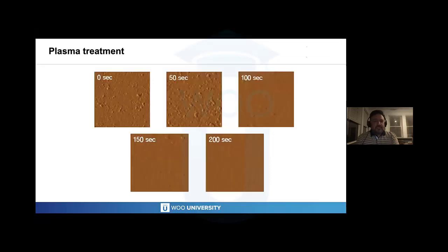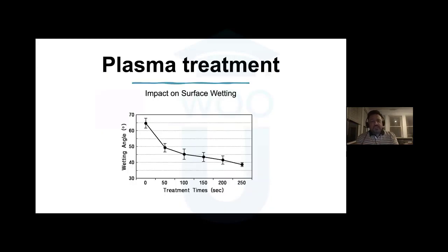And you can see the impact of plasma treating a lens surface after a period of time. It certainly gets away a lot of that extra residue. And the wettability of any lens, of course, like I said, is impacted by the smoothness of the surface. And when we've got a surface which is full of micro deposits or residue, that is going to affect wettability, no question about it. Here's a chart that shows the impact on surface wetting of plasma treatment. When we do run plasma times of at least 50 to 100 seconds, you can see that we affect that wetting angle by almost 50%. We can improve the wetting angle of the surface of the lens from 70 to 40 on a comparable material by doing this hyper cleaning, if you will, through plasma treatment.